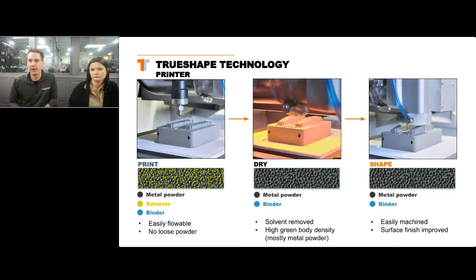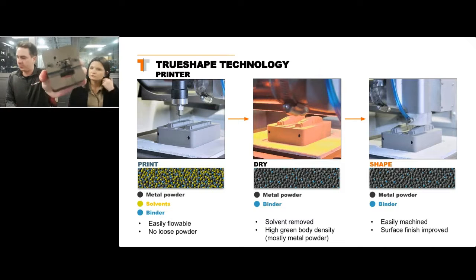Another critical thing about this drying step is it's making the material firm enough that now we can machine it. So every single layer inside of this printer, we're going to print, we're going to dry, and we're going to machine. Every layer, we're going to machine perfectly flat. Every 10 layers, we're going to contour mill. Since the part is very soft when we're doing this, it's essentially a foam, and we're taking very small depths of cut. Since we're printing and machining, we can use these really, really small cutting tools that normally you would struggle to use on a tool steel, like a 6-thou ball end mill. We're using off-the-shelf cutting tools, 20 different tool changers inside of the machine, so we can use a variety of different tools to really give you that sharp feature resolution that you would not be able to do with other technologies.